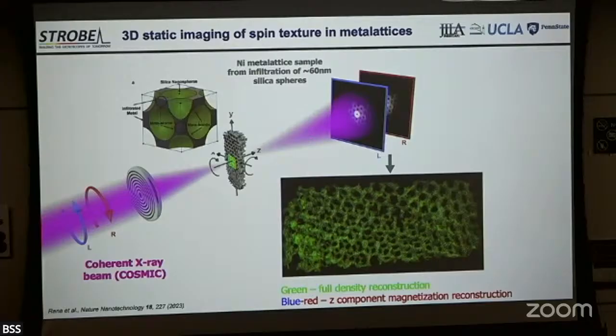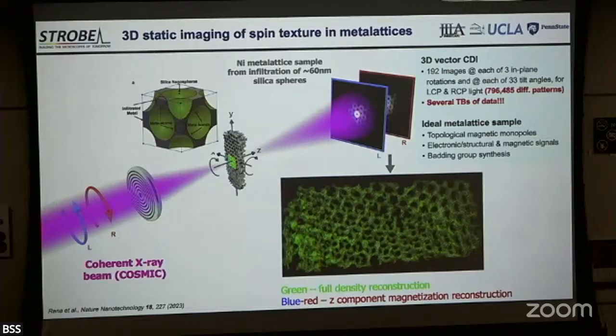This experiment was done during COVID. And I remember Emmett Keyting, one of our postdocs at the time, had to, John's group FedExed us the sample from Penn State. Then Emma took it to our electron microscopist who FIBed the sample, then drove to the Bay Area, did 2 weeks of quarantine with her brother, and then brought it up to the Advanced Light Source so we could actually do the imaging, because it's a lot of data. It's almost 800,000 diffraction patterns that then you have to analyze.